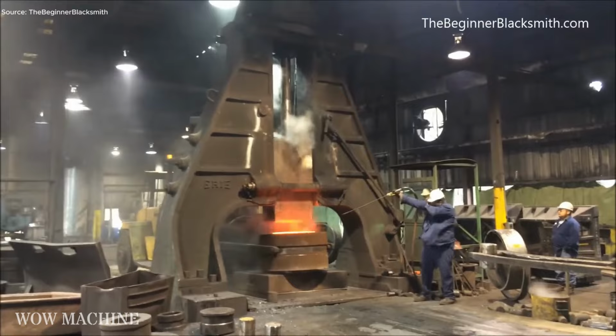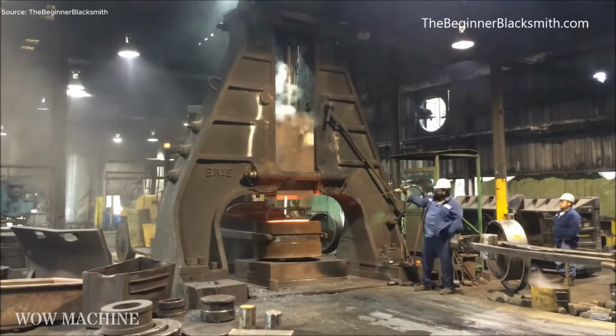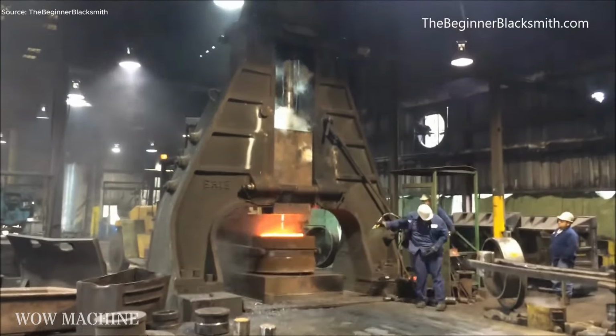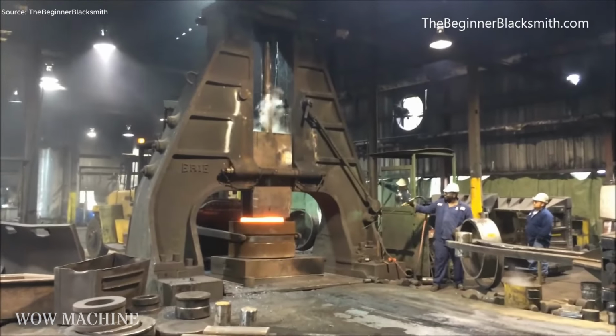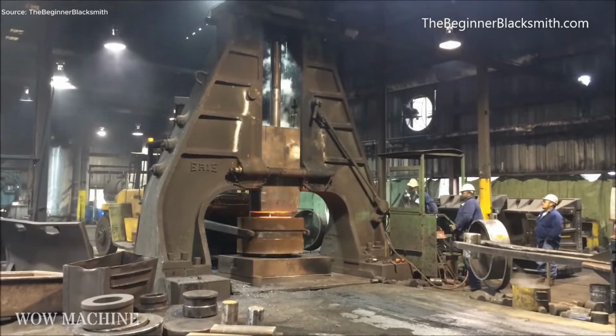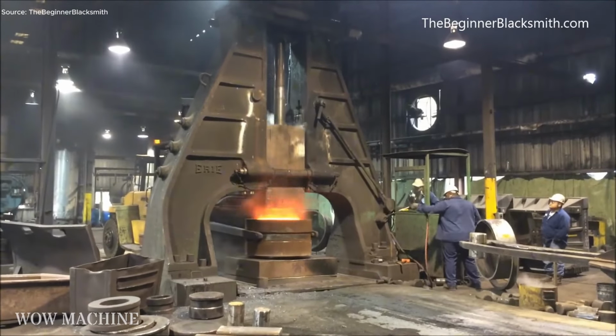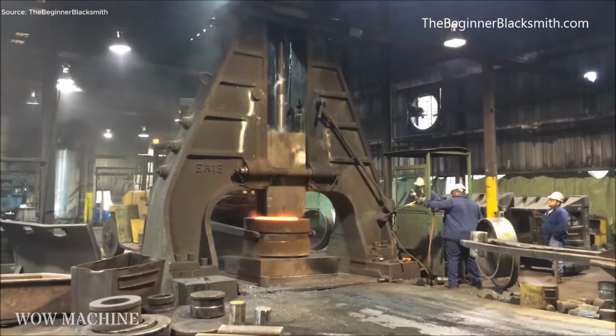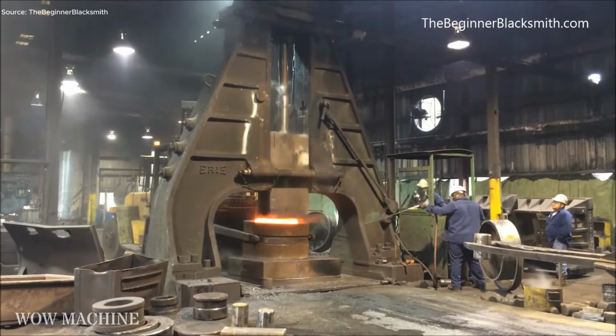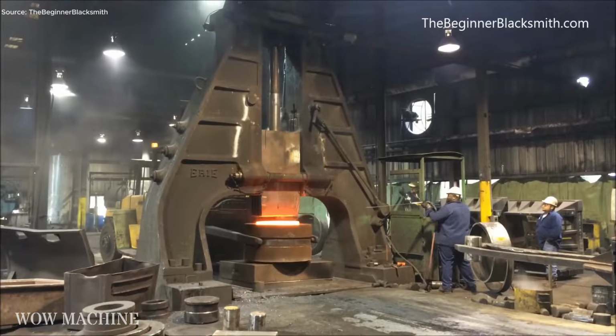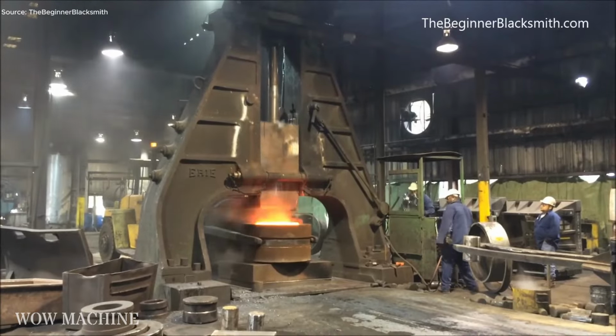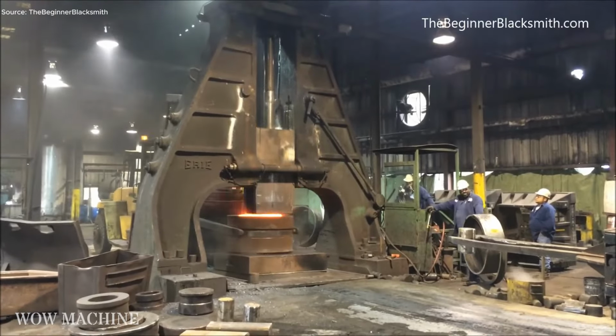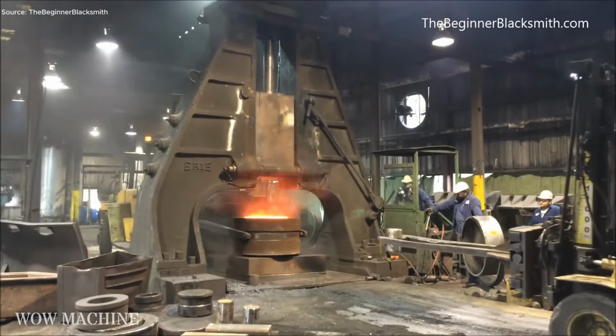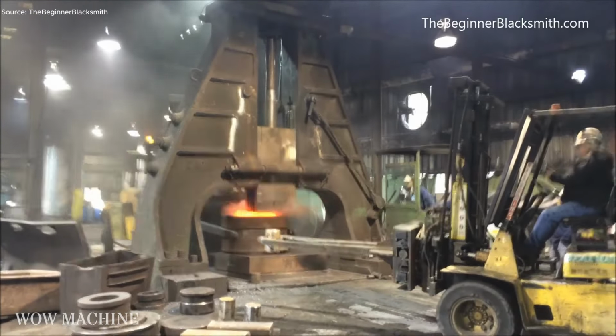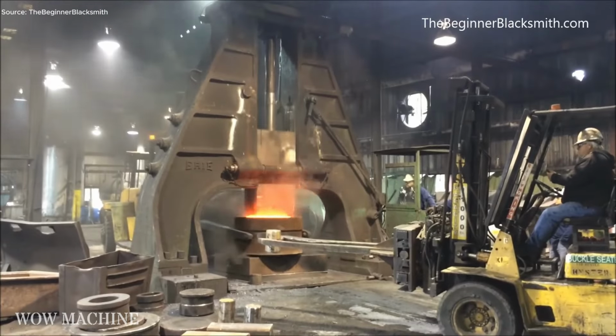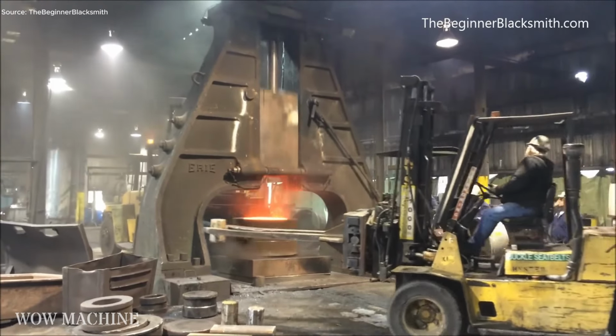With every blow, the hammer delivers controlled tons of force that elongate, spread, or reduce the billet according to the forging plan. Operators continuously rotate and reposition the workpiece to maintain uniform grain flow and prevent internal stress concentrations. The repeated high-energy impacts refine the steel's microstructure, increasing toughness and directional strength. For large cross-sections, the process may include multiple heats and progressive reductions to reach the required dimensions. The result is a precisely forged component with improved mechanical properties and structural reliability.